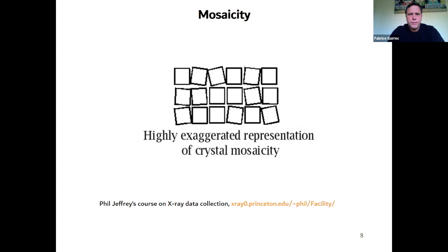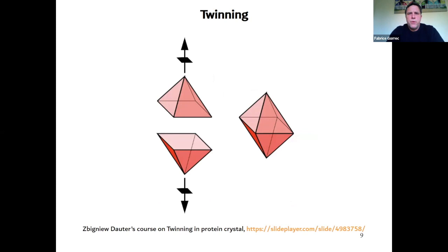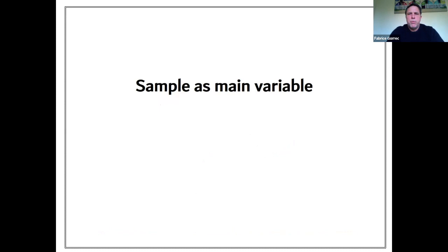Another crystal pathology is twinning, and here it's represented by a kind of simple case, so to speak, where basically the crystal is made of two crystals that grow in different directions. There are more tricky cases than that, and that could prevent you from solving the structure in the end. So you may see a nice diffraction pattern, but you would have problems solving the structure because of the twinning. So the sample is the main variable when you try to tackle protein crystallization.